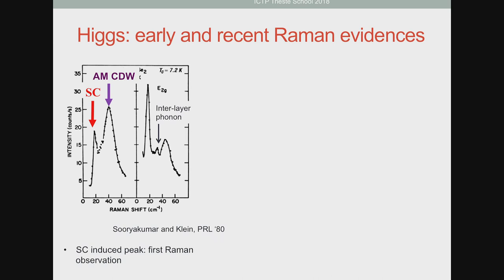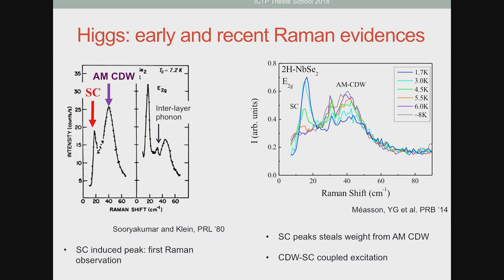When you cool down below TC, so this is the amplitude mode of the CDW phase that I showed you previously, and right below it in energy you have the emergence of a sharp peak, which could be interpreted as a superconducting gap energy 2Δ. Now, what is striking about this superconducting mode is the way it interplays with the charge density wave mode. And this is most easily seen by doing a careful temperature-dependent measurement across the superconducting transition temperature.